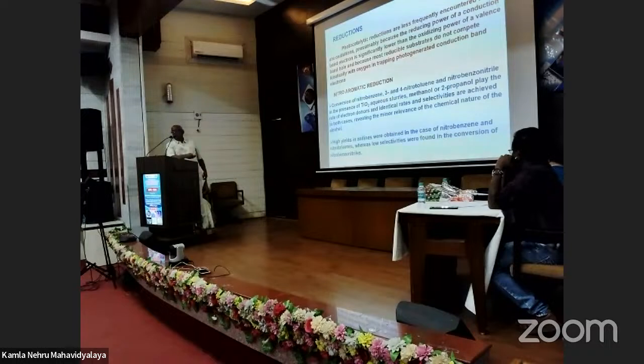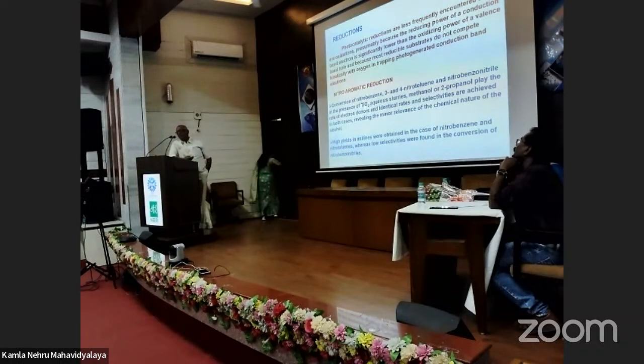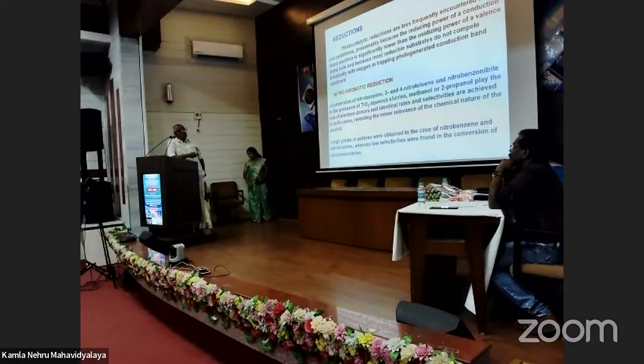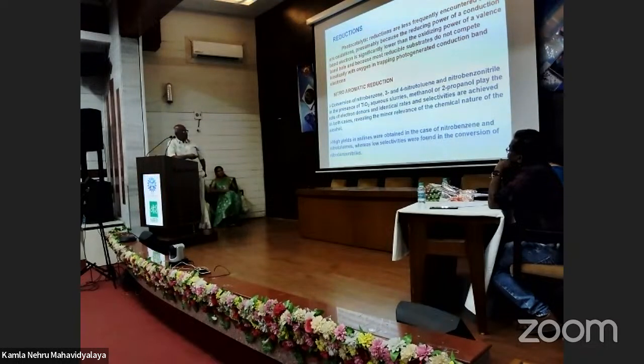And the reduction is more important. Generally, the photocatalyst is mainly used for oxidation. Suppose in an aqueous solution you irradiate a pollutant using a photocatalyst, it is completely oxidized. Whereas if you use it in non-aqueous solvents, you can have other reactions. Reductions are very rare, but reduction can be done because once you separate the hole, the electron can be used for the reductions. Otherwise, normally reductions are very slow. So nitro, NO2, can be reduced to aniline. There are so many examples.